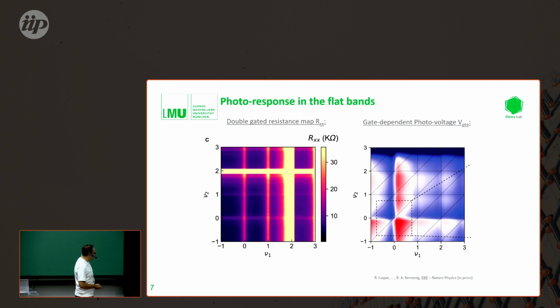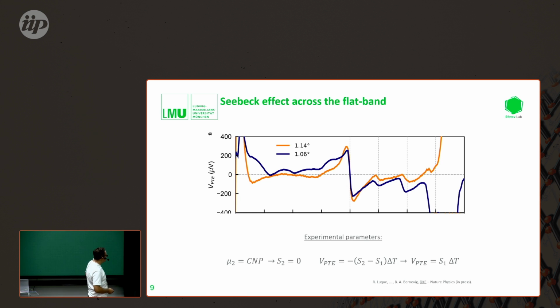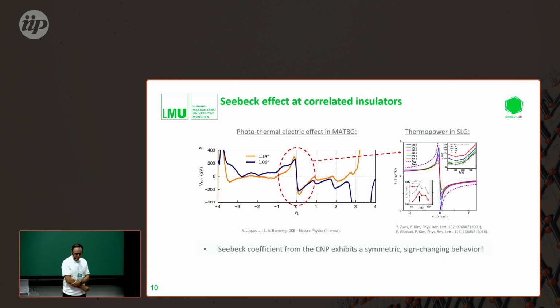So now, to analyze the signal also at integer fillings, we can take these maps and take line cuts where we tune one of the regions of the device to a zero Seebeck coefficient, and analyze the line cuts here. The thing that we see in these measurements is the following. If you look at the charge neutrality point, it behaves like what is expected from the Seebeck effect when you tune from the electron to the hole side. The Seebeck effect is positive on the hole side and negative on the electron side, and it undergoes a symmetric S-shaped transition when we tune across the charge neutrality point. This is exactly the same behavior that people like Philip Kim worked out in the past on single-layer graphene.